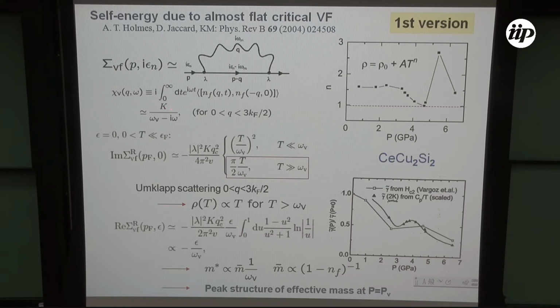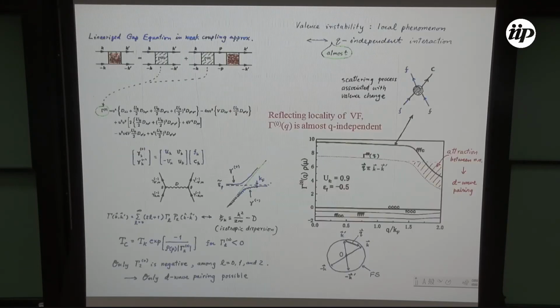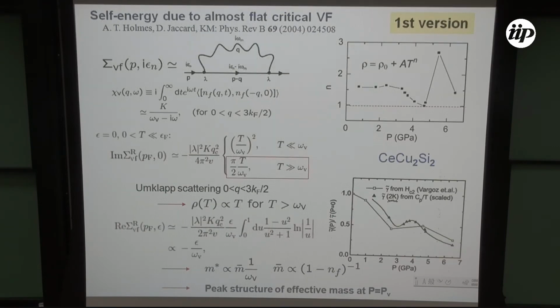Next, the fluctuation is essentially Q independent, so that phenomenologically we can discuss the effect of valence fluctuation on the self-energy. Then, using this almost flat, almost Q-independent susceptibility, we can obtain the imaginary part of sigma, which is proportional to T at high temperature region. If omega V equals 0, this temperature dependence dominates, which is the origin of the T-linear resistivity at the critical point. And also, the real part gives another enhancement, inversely proportional to omega V.